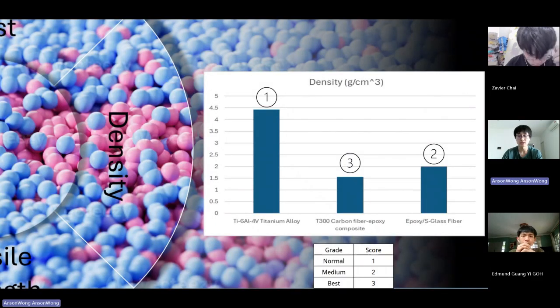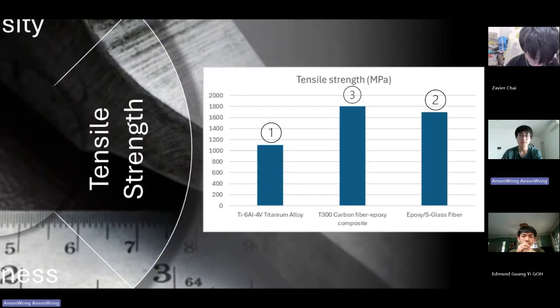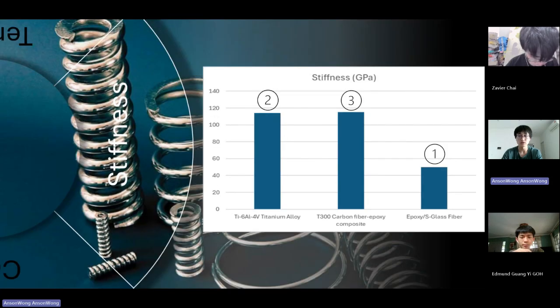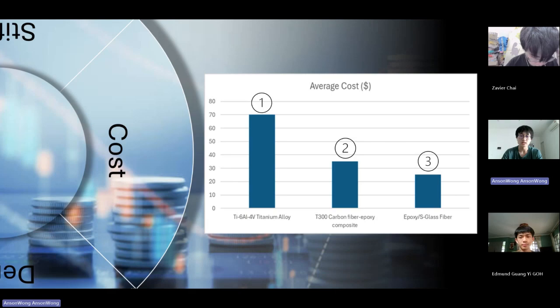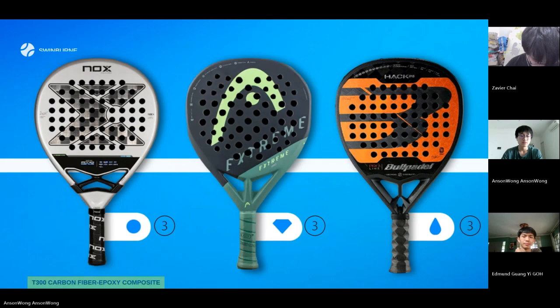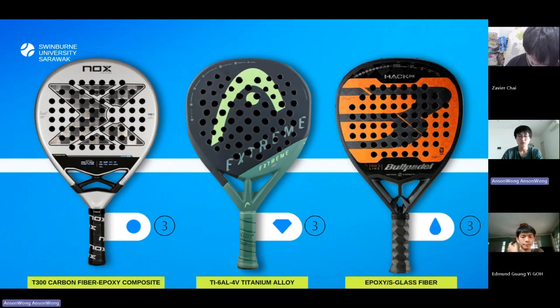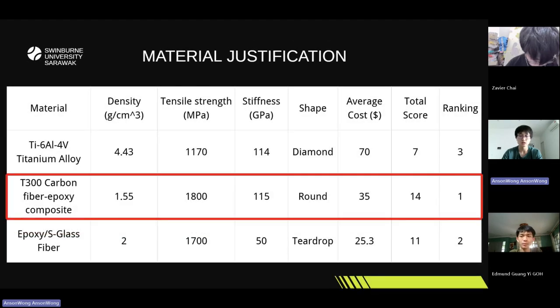On the chart, it can be observed that the T300 carbon fiber epoxy composite has the lowest density while exhibiting the highest tensile strength and highest stiffness among all the materials. Only its average cost is slightly higher than the epoxy S-glass fiber and is given 2 points only. For the frame geometry, each material is assigned the most suitable shape to maximize its performance, and therefore all are given 3 marks. After calculating the total mark, T300 carbon fiber epoxy ranks first and is the most suitable material for a tennis frame. Now I'll pass time to Edmund.